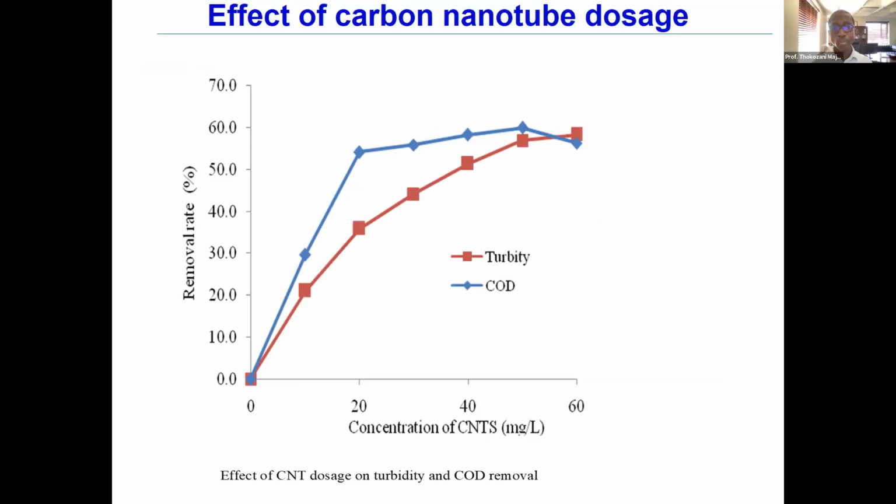Yeah. What I was saying here is we just wanted to see the effect of dosage here on the turbidity removal and also COD removal. But what we see is as we increase the carbon nanotubes, there came a time when the turbidity and also COD removal started going down.